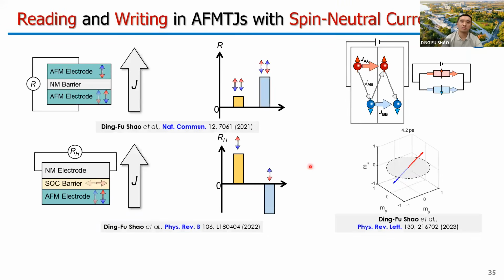In conclusion, previously we usually considered that only spin polarized currents can generate the spin-dependent transport properties used for information read in and read out for spintronics. But we found, in contrast to this common expectation, that spin-neutral currents can be very useful, especially for antiferromagnetic spintronics. We can use them to drive the tunneling magnetoresistance, the tunneling anomalous Hall effect, and the spin transfer torques in antiferromagnetic junctions.